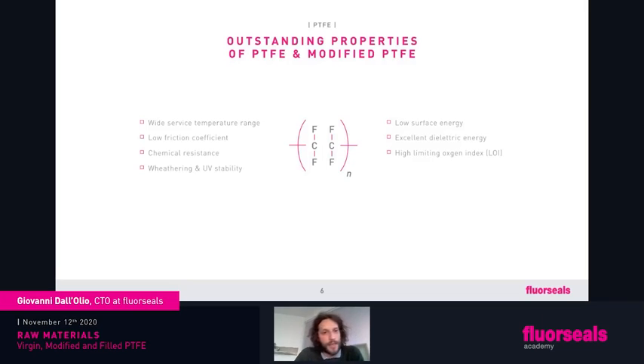The chemical resistance, again, like the service temperature, there is no other polymer on the market that has the same chemical resistance as PTFE. Basically, PTFE is resistant to everything. There are no known solvents that can attack PTFE. Also, another important property is the UV stability, the weathering.